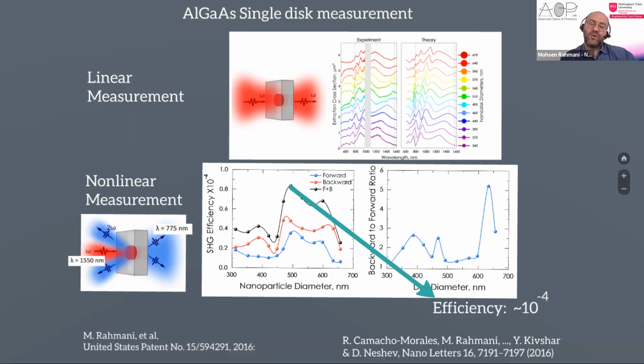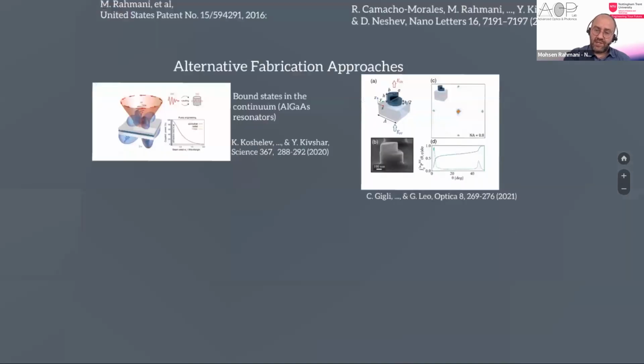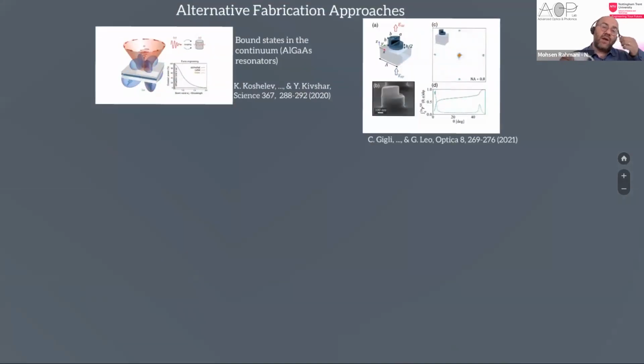And in this nanofabrication technique, which I'm not explaining here, but if you are interested, you can go and see in this patent or in this paper. So we managed to have these III-V semiconductors on very thin glass substrate, then get both forward and backward second harmonic generation. So it was followed by several other successful approaches to generate these III-V semiconductor nanoparticles on glass, again by a group of Giuseppe Leo and also Yuri Kivshar.